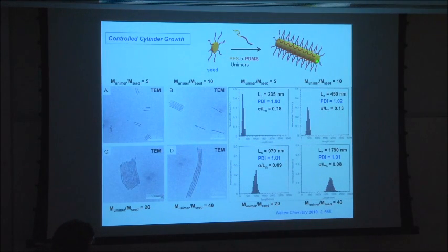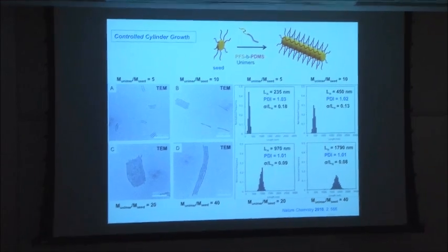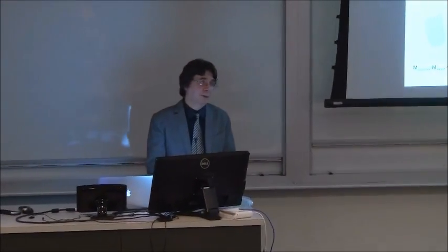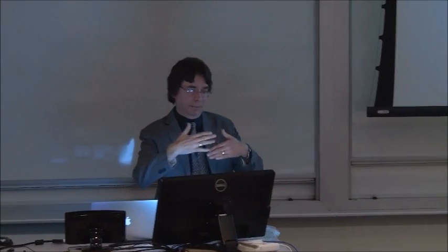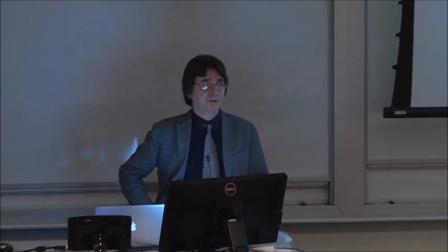So we think probably at the edge of the core there's disorder, and you have an amorphous region around the outside, which is probably where the chain folding takes place, because we know how the chains pack in these cores, and the diameter of the core is about a third of the extended chain length of the core-forming block. So there's clearly chain folds. And so there's got to be an amorphous region around the outside. So actually where the coronal chains are attached, almost certainly it's in an amorphous region. So it may not have an effect, but I think it's a really interesting point, and it may be possible to control things if you can make rectangular structures. With platelets it might be relevant, for example.